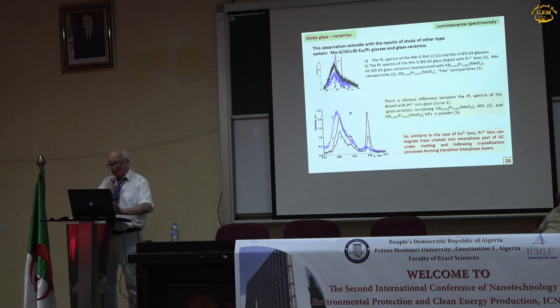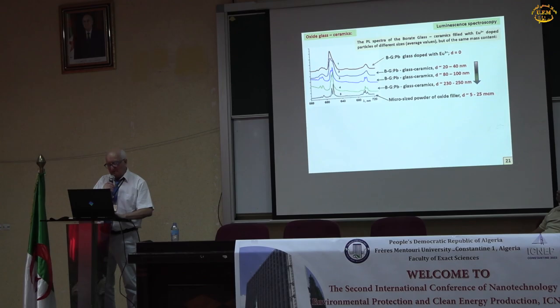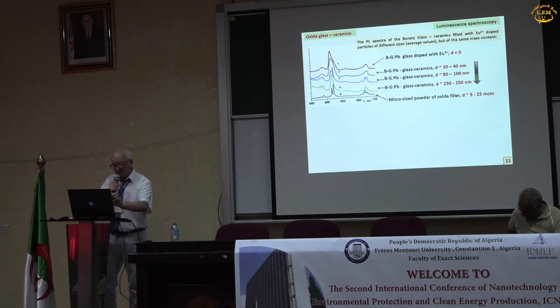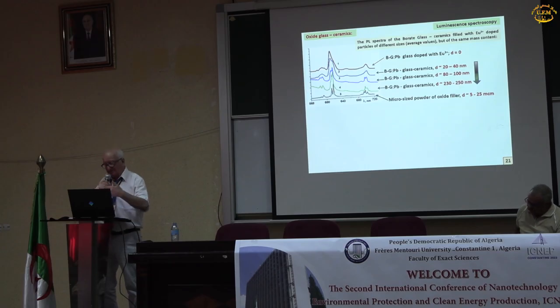This is the data obtained by us for another type of the composite. They are similar to show it before. There's some other experiment of this type where we change the size of the nanoparticles. This is the luminescence of europium 3+ ions at the top in the glass, and at the bottom you see the luminescence of the europium 3+ ions in powder, crystalline powders. And in the middle you see the spectra of the glass ceramics where particles of various size were embedded.